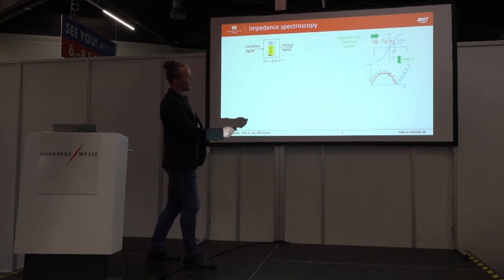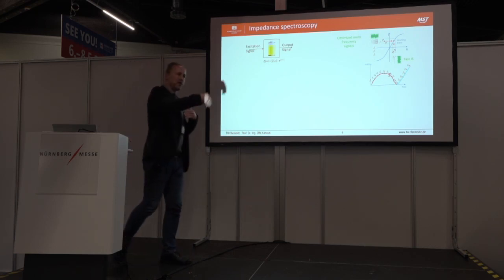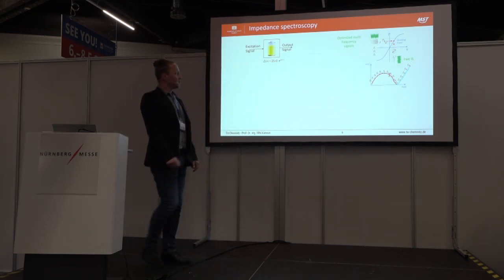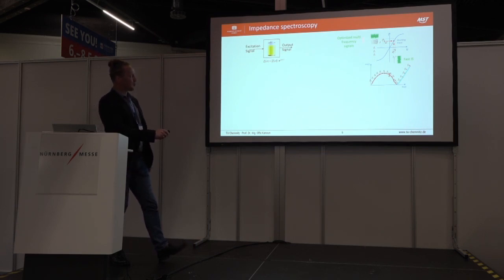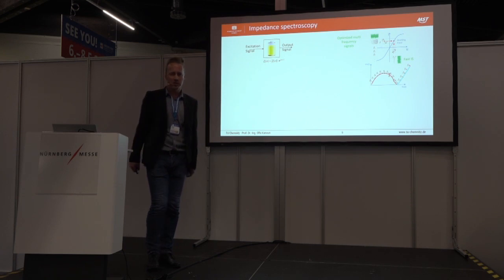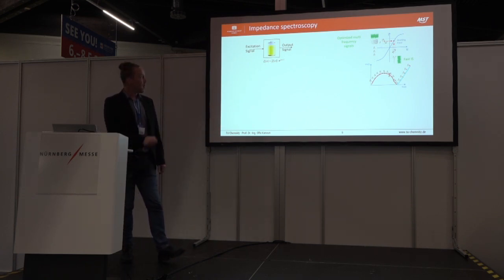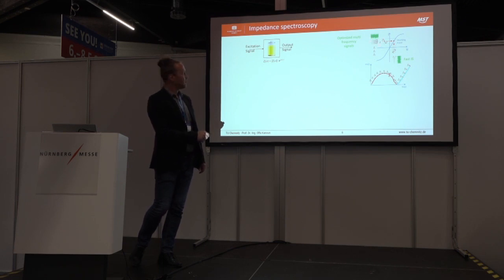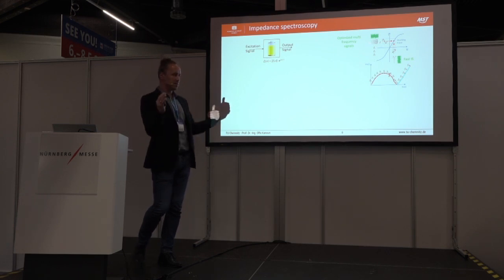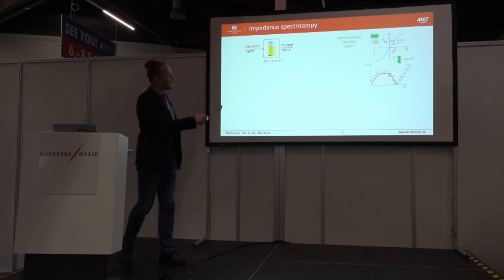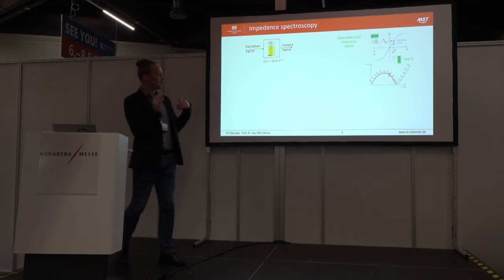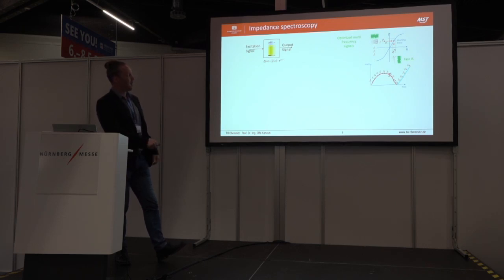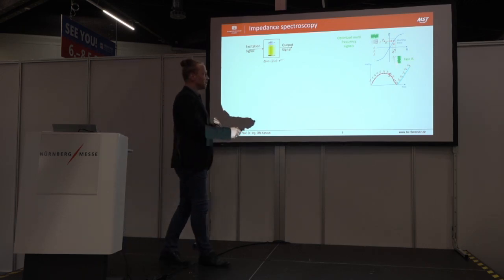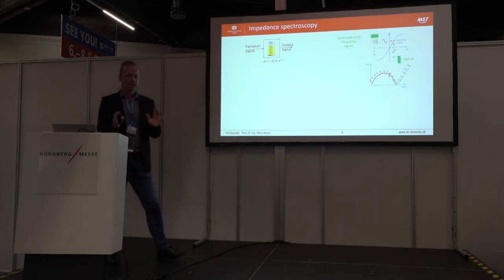If you take a look, you have here now a sweep of a sinusoidal signal. You put one frequency after another, so you have a long measurement time. For fast impedance spectroscopy, for sure, there are a lot of opportunities, a lot of approaches to reduce the measurement time. Here is only one example, multi-sine. You see here 2 periods of the smallest frequency, the longest period duration, and we put all the other frequencies into this time window, and we apply at the end a multi-sine signal, and it is possible using signal processing to analyze each frequency point separately.